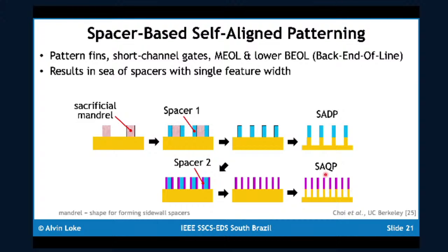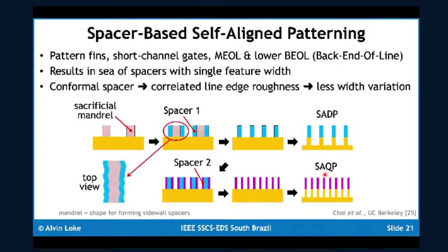One benefit of these techniques is that because the spacer that's deposited is a conformal process, the line edge roughness of things patterned using these spacers is going to be a lot less, leading to less width variation compared to if you were to use photoresist, where the line edge roughness on the left and right edge are not correlated, leading to more width variation.